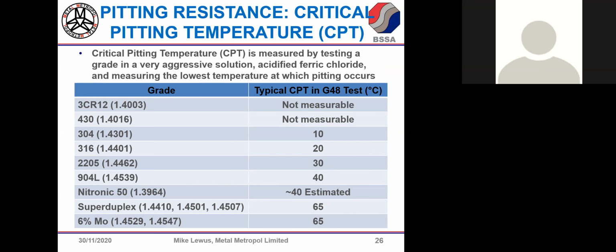Another metric that goes with the PREN number, or the pitting resistance equivalent number, is the critical pitting temperature. That's the temperature below which you won't get pitting. And you can immediately see on this table, going from 430, which is a ferritic grade, to 304 and 316, the big two austenitic grades, as we move down that table, the critical pitting temperature goes up. So you can see immediately 304 is very likely to pit above 10, 316 above 20. So you're in a safer and safer ballpark. 2205, a duplex, we wouldn't expect to get pitting below about 30 degrees, so you'd be very safe with that, even in our more tropical zones.